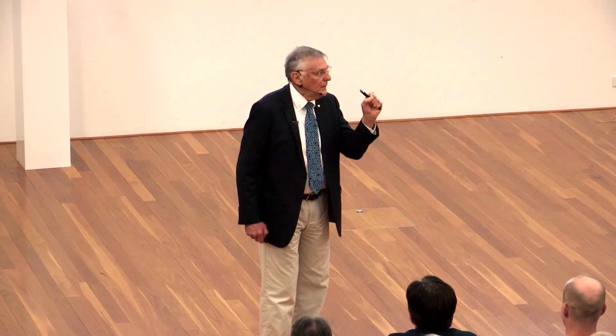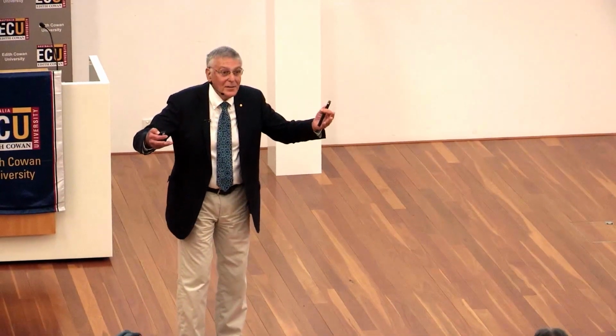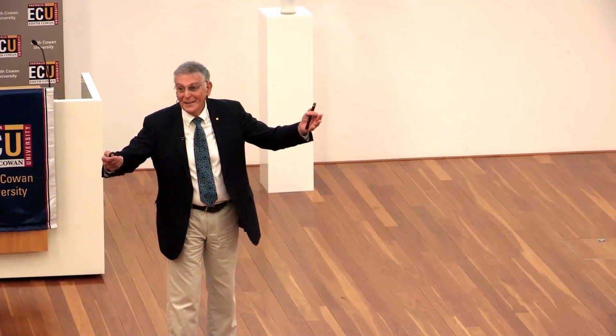Why couldn't we have it? Because they were very, very small. And in those days, we did not have a small enough beam, which we have today, to take a diffraction pattern from a crystal which is 1 micron in size. We needed to grow larger crystals. But in order to grow large crystals, we needed a stable composition from which you can grow large crystals. As large as 1 millimeter is good enough.